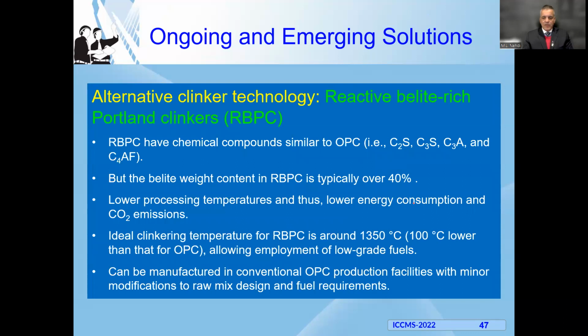Another alternative clinker technology is the reactive belite rich Portland cements. It somewhat relates to the topic I was discussing. So we said clinker would contain mainly dicalcium silicate, tricalcium silicate, tricalcium aluminate, and tetracalcium aluminoferrite. So this is the belite phase. So belite rich cements, usually around maybe 40%, because normally, belite is not that high in normal cements. You find C3S as a major ingredient, maybe because, as structural engineers, we're addicted to f'c. We want to have the 28 days compressive strength, and therefore they give us cements rich in C3S to produce early strength, and they grind the cements finer, and so on. High belite cements would be somewhat different. I mean, they hydrate slower and so on because of that richness in C2S.